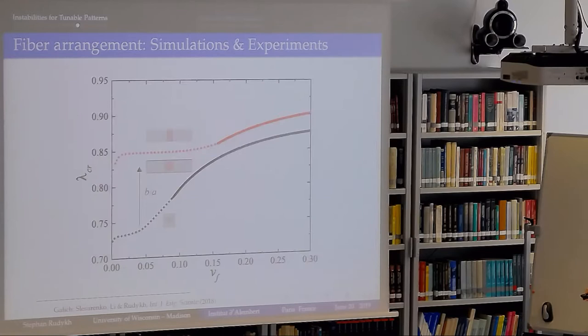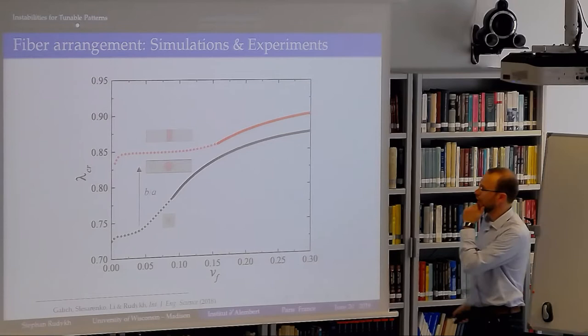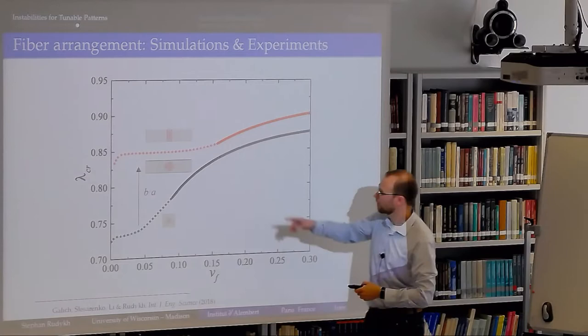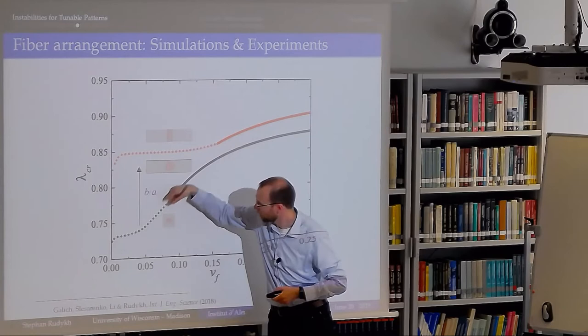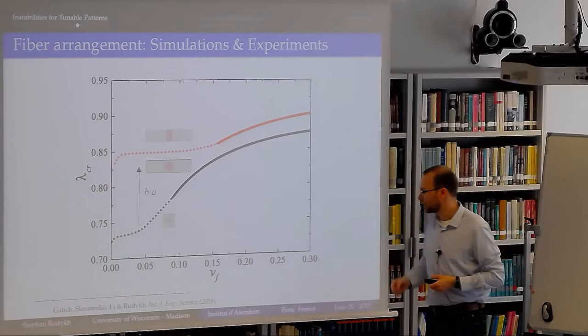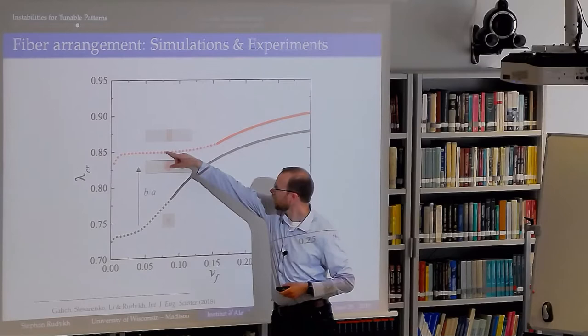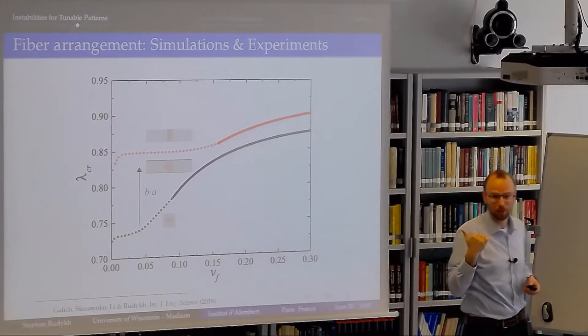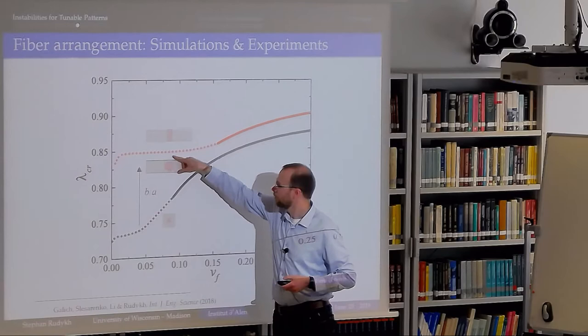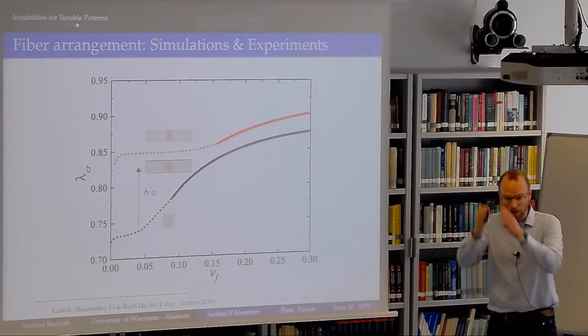So one more thing that we also saw here is that, interestingly, there appear two lower and upper bounds when we change the aspect ratio. Here you're bounded by the symmetrical case of the circle in the quadratic unit cell, when they are equal to a. But at the upper part, you're bounded by the analytical results of the laminate. Which is interesting, and it actually makes sense. If you think about it, when you put these inclusions very close together, they start to act in a way as a reinforced layer, as a laminate.